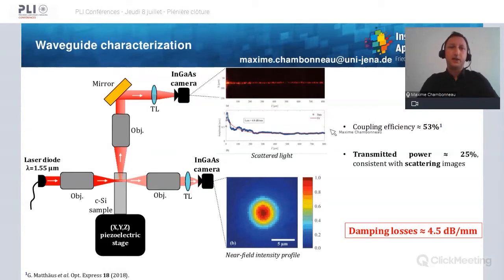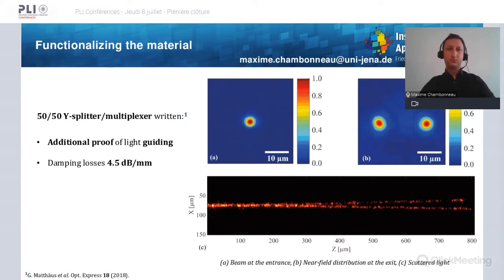With this setup, we have found that our waveguides show a coupling efficiency of 53% and a transmitted power around 25%, which is consistent with the scattering images. So to conclude on this, we have found some damping losses around 4.5 dB per millimeter, which is the lowest for laser written waveguides inside silicon to date.